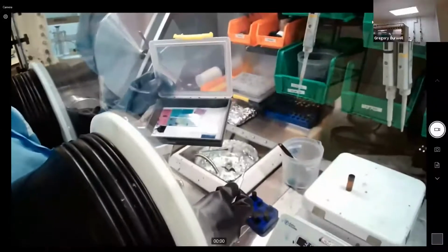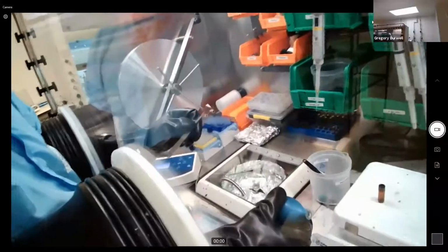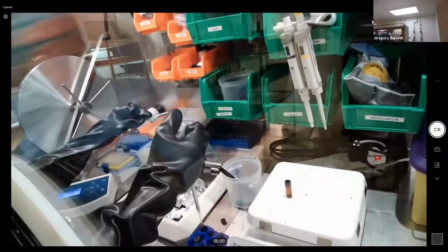what we'll show you is some different types of films that Wei has already cast. You can see some of the pretty colors resulting from the films. So these will be cast onto substrates, such as the one he's holding up now. These will typically have a transparent conductive oxide like ITO as part of the device. He'll make sure they're extra clean, and he'll load them on to the spin coater. And Wei would have already prepared a solution with an organic material in some solvent. And the concentration of that solution, together with the spin speed, will give us a very precise thin film thickness.